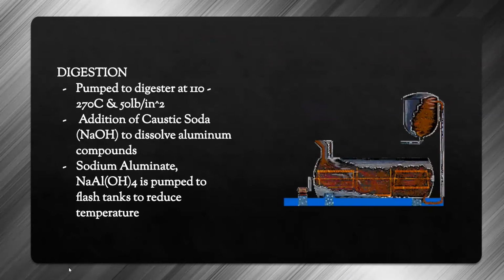In the digestion process, the slurry is transferred to the digester tank and heated at 110 degrees Celsius to 270 degrees Celsius at 50 pounds per square inch pressure. Additional caustic soda may be added to the solution to dissolve the remaining aluminum compounds. The resulting solution here is the sodium aluminate, which is pumped to a series of flash tanks to reduce the temperature.